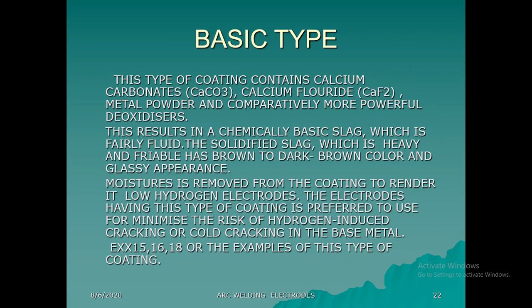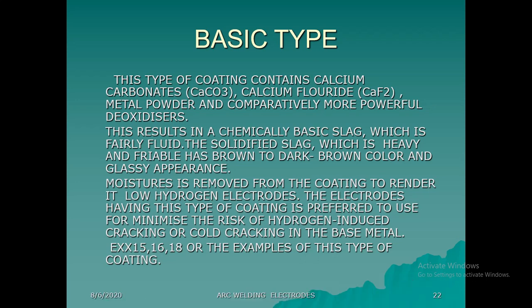Now the very important one is the basic type, which you use in industry. This type of coating contains calcium carbonate, CaCO3. You have to remember what is there in this type of coating: calcium carbonate, calcium fluoride, metal powder, and a comparatively more powerful deoxidizer, meaning very powerful for deoxidation. This calcium carbonate and calcium fluoride remove the oxygen from the area. This results in a chemically basic slag which is fairly fluid. The solidified slag is heavy and friable, with a dark brown color and glassy appearance. This appearance is also very good.